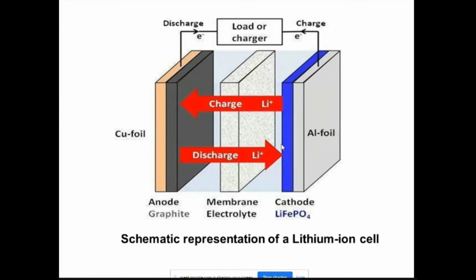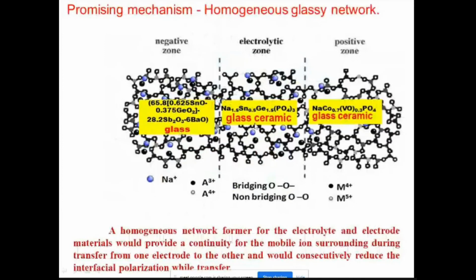interface problem. So in order to improve its efficiency, if you are able to make an electrode, anode or cathode, in a glassy material, one can enhance the battery performance. That's what people are working on in the case of batteries. For example, you see a glass material, glass ceramic material. A homogeneous network former for the electrolyte and electrode material would provide a continuity for the mobile ion surrounding during transfer from one electrode to the other, and would consequently reduce the interfacial polarization while transfer. So nowadays, most of the people are working on how to prepare a battery based on only amorphous material, because electrolyte is supposed to be amorphous material.